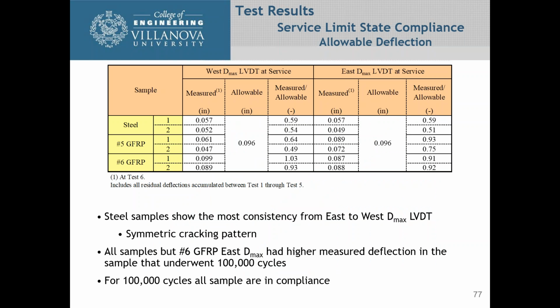So in summary, we'll show a table here, and you can see the ratios. We had LVDTs on the west side and on the east side, and you can see that all the ratios except for one were less than 1, and we had one location where it was just over 1. So pretty much after 100,000 cycles, you can say you're still within compliance for allowable deflection.